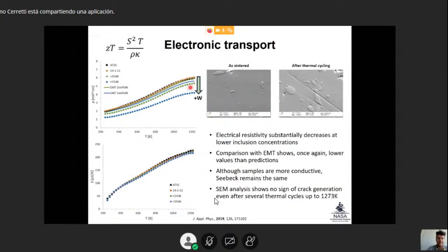So here again we can see that, yes, indeed the 5 volume percent already has a drastic reduction of the electrical resistivity. Using again the comparison with the theoretical model, we saw that the measured values are way lower than what we should expect for such low inclusion. So this seems to be a general trend, at least for metallic inclusions in this specific thermoelectric material. Therefore, there's still something that we are not getting right. The theory which is generally used to predict the properties of the materials is definitely missing something. There's something that it is not catching.